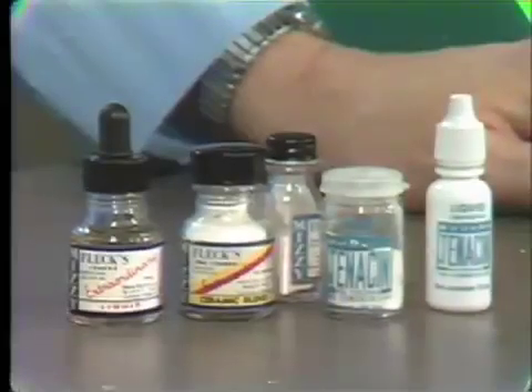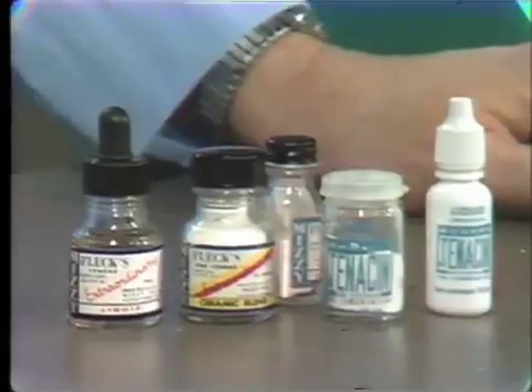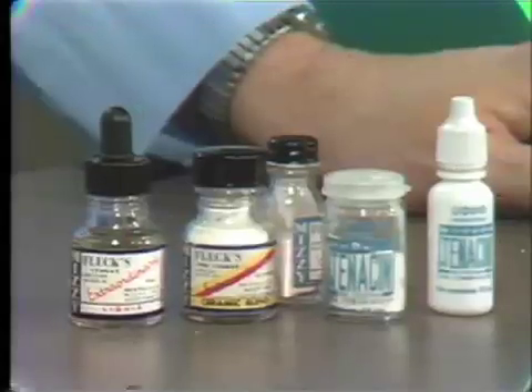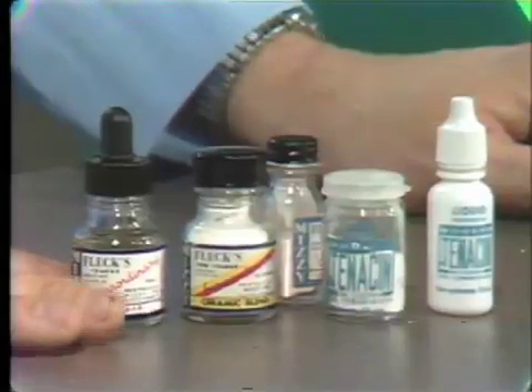Now I'd like to talk about the zinc phosphate cements. The zinc phosphate cements are rather strong. They have a crushing strength of 13 to 14,000 pounds. They, however, are acid, and they tend to irritate the pulp. So it's necessary to varnish the teeth before you use these zinc phosphate cements. They are mildly soluble in saliva.